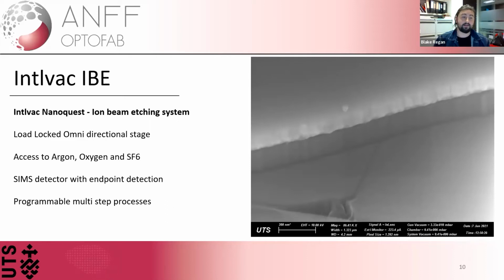We do also have a SIMS detector, which allows us to do endpoint detection, as well as a very low amount of chemical analysis. So we'll be able to tell you what ions are coming out of there. You can take out of that information a ratio, but it is dependent on the ratio of the detector sensitivity. So mostly that's going to be used for endpoint detection. What I mean by that is if you have multi-layer materials, a good example being aluminium, silicon, aluminium, silicon, aluminium, silicon, you'll be able to not only detect when you cut through those layers, but it'll be able to end the current process and also start a new one.